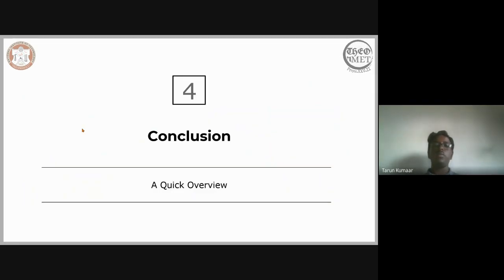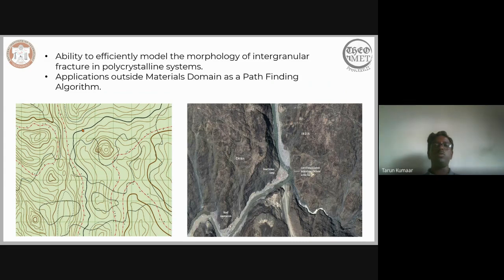So finally, coming to the conclusion, we were able to efficiently model the morphology, so how the structure looks, for intergranular fracture in polycrystalline systems. The advantage of this compared to, say, molecular dynamics simulations is that this is very computationally efficient, and you're able to get very similar qualitative results. And there are also applications outside the materials domain, which we want to further look into.